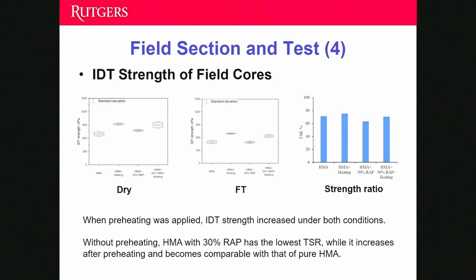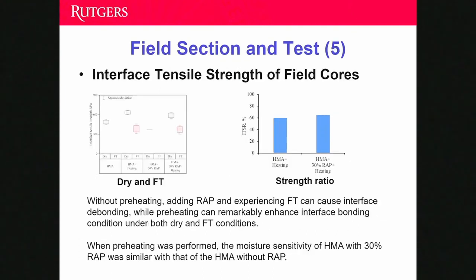This indicates the potential of using RAP material in pothole repair, but we still need to evaluate the interface and also the abrasion resistance. And here is the interface tensile strength of field cores. We found that without preheating, the asphalt patching material with RAP material failed after freezing soil conditioning. Even before we did the mechanical testing, it failed because of the freezing soil. And when we applied preheating, the field cores were still intact after freezing soil conditioning.